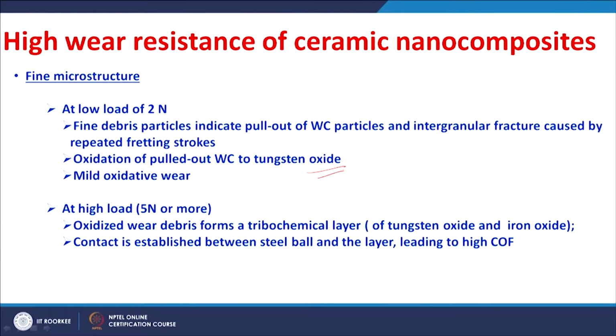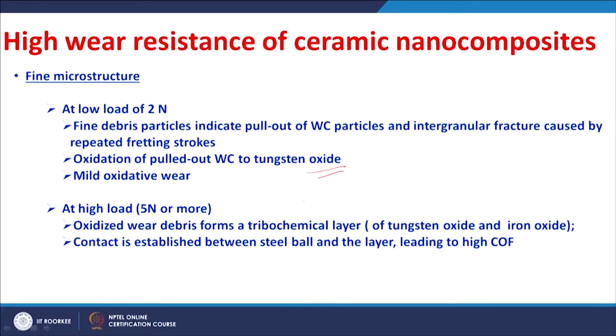So, there is a possibility for oxidation. The pulled out tungsten carbide particles are oxidized to tungsten oxide. So, we can infer that there is a mild oxidative wear occurring at the contact at lower load conditions of 2 Newton, whereas at higher load, 5 Newton or more, these oxidized debris form a tribochemical layer. The tribochemical layer is rich with tungsten oxide or iron oxide. Once this layer is stabilized, the contact is actually between the steel ball and the layer, not between the steel ball and the tungsten carbide zirconia surface. The friction is happening between the steel ball and the layer. Because of that you get a higher coefficient of friction.